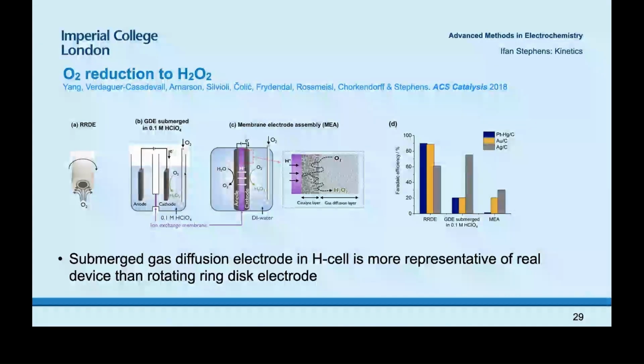So what we found worked better was to take gas diffusion electrodes and submerge them into a stagnant electrolyte. We found, especially when measuring selectivity for oxygen reduction, that this was more representative of a real device, the MEA, than the rotating ring disk electrode setup. So it is important to bear in mind that what works well in the rotating ring disk electrode setup doesn't always work well in a real device.